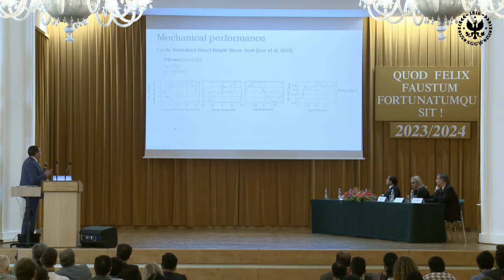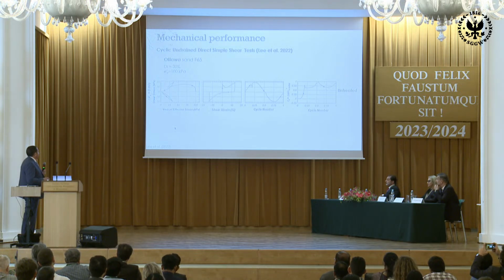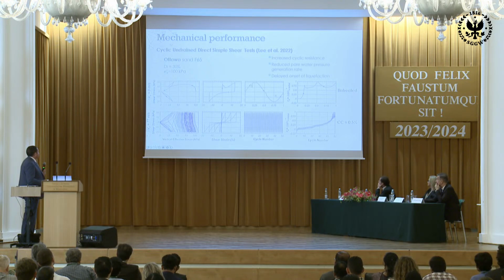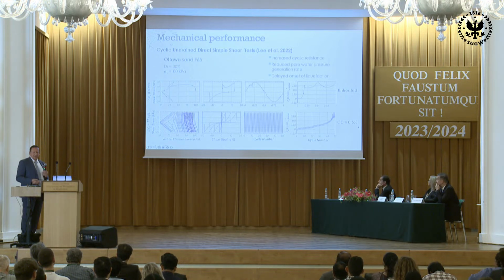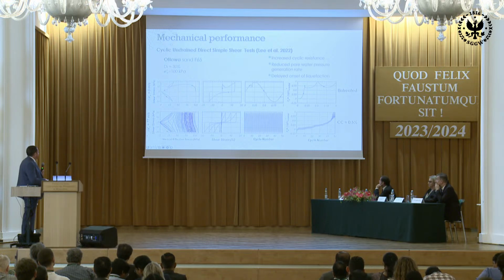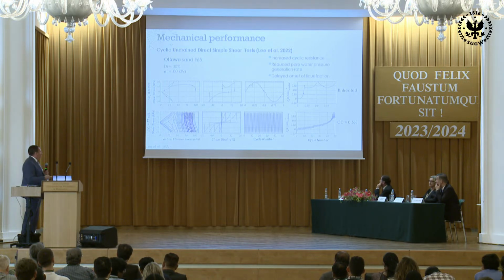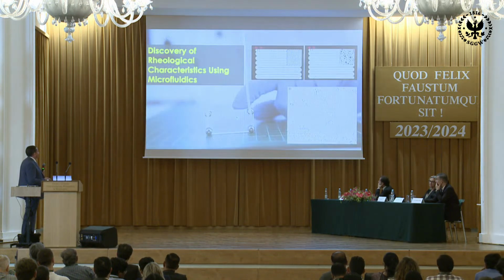Last experimental thing, this is the only result that is not coming from our group, is a cyclic direct shear test, where the authors, Lee et al., tested first a material that is not treated, and then tested the same cyclic behavior of the material after a small treatment, 0.5% of calcite content. You see the number of cycles needed to get to liquefaction is huge. With this, we are decreasing significantly the liquefaction potential with just 0.5% of calcite precipitation.